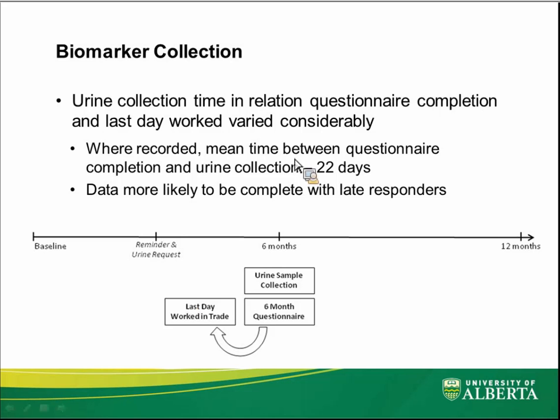So again, here's the schematic that I showed earlier, but the urine collection time in relation to the questionnaire completion, as well as the last day work, varied quite considerably. It wasn't recorded in all cases, which was the first challenge, but where it was recorded, the time between completing the questionnaire and collecting the urine sample averaged 22 days. So they were quite far apart in reality.